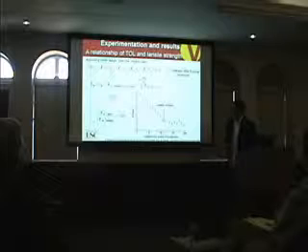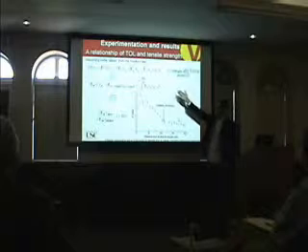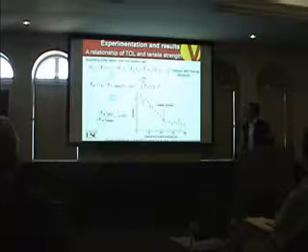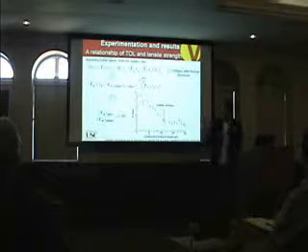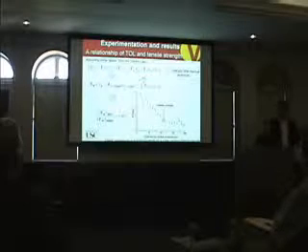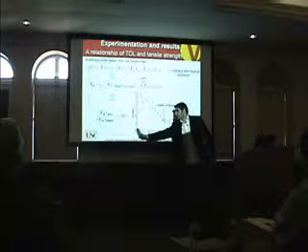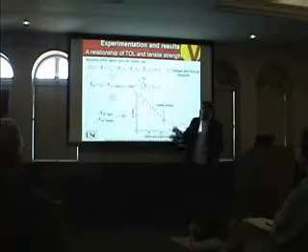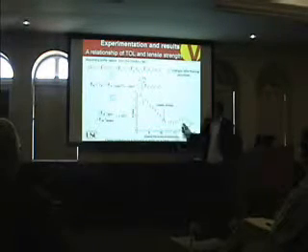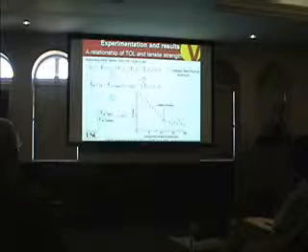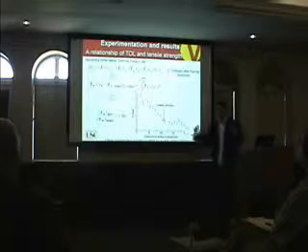So why did that happen? Assuming Hooke's law and brittle failure, the only term that changes in this equation is the matrix modulus due to the oxidation. So this is the distribution of matrix modulus. This is the surface of our material, and as you go in, you see that when the matrix oxidizes, the modulus increases. But the oxidation is only 100 microns, a small portion compared to the whole structure, so it didn't change the whole tensile strength of our material.